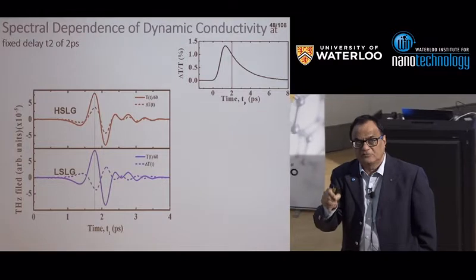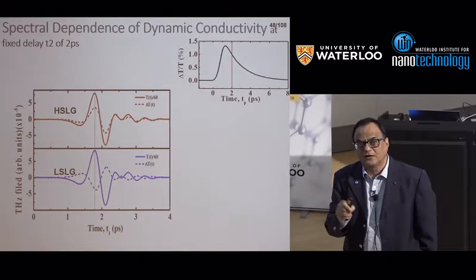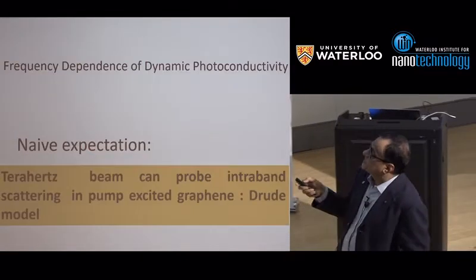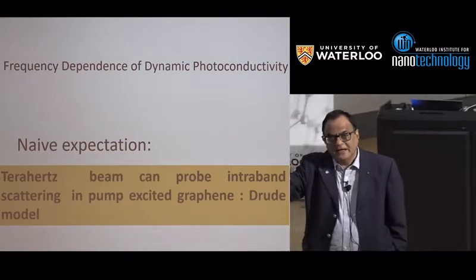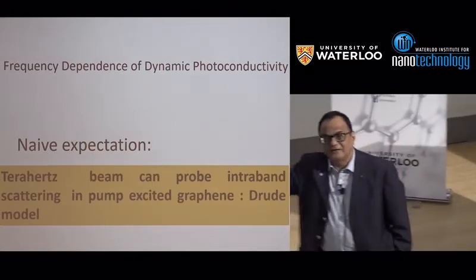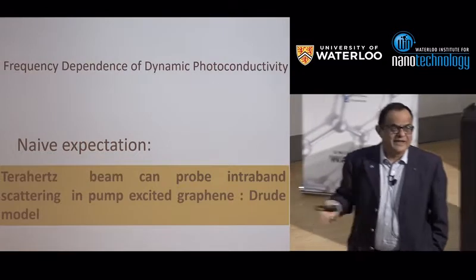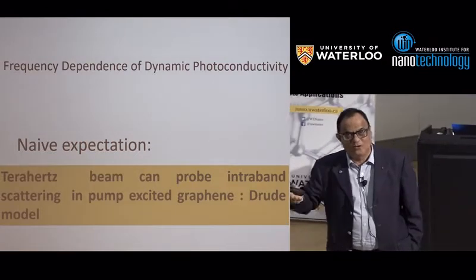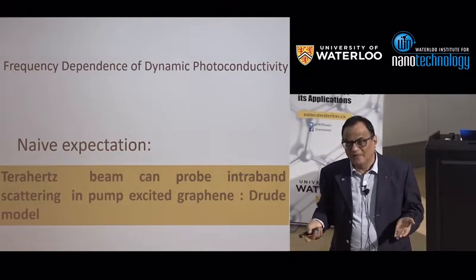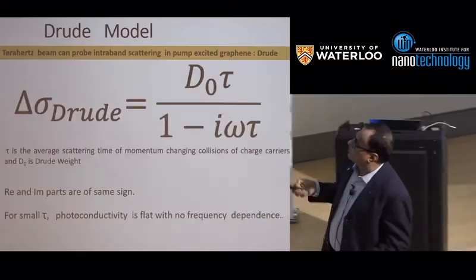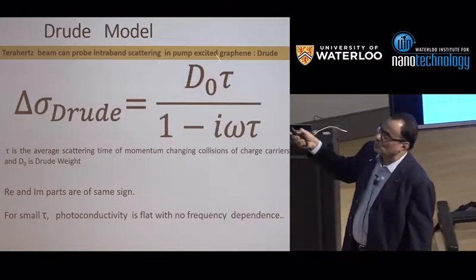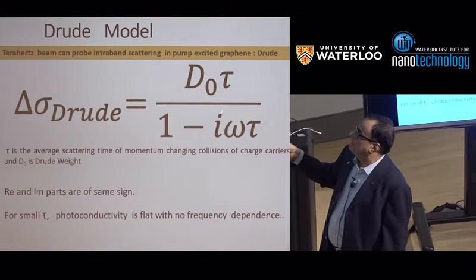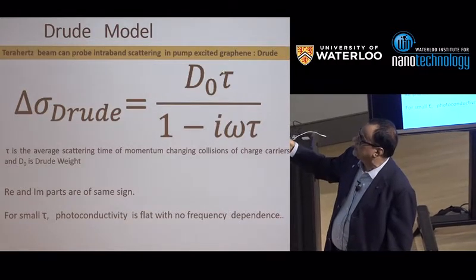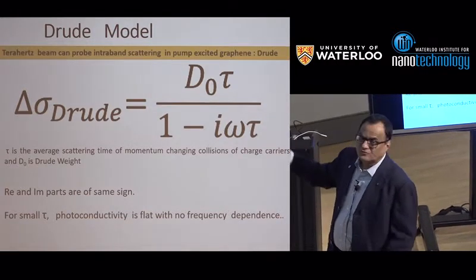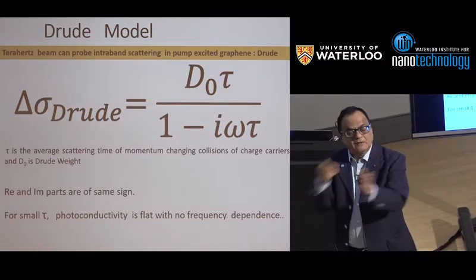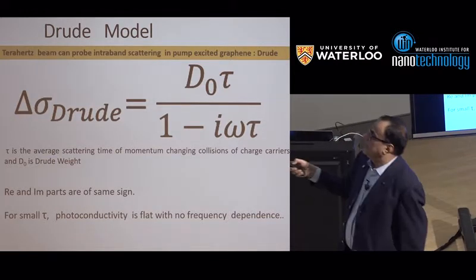the photoconductivity spectrum. We want to measure how photoconductivity varies as a function of frequency at different delay times and at different temperatures. Now again, what is our expectation? Drude law, because we grew up with Drude law. So we will say, well, the photoconductivity will simply be a Drude law, and you will have a momentum relaxation time entering here. This is the Drude weight, which of course you have to do carefully for graphene because these are Dirac electrons, and that's all.